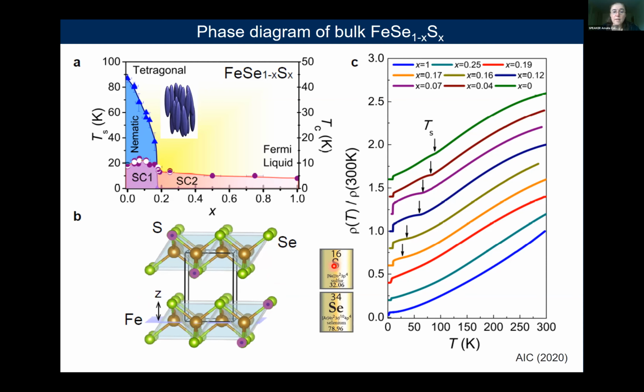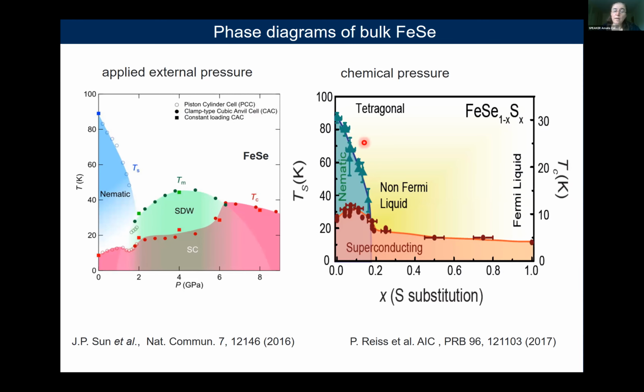So as sulfur is smaller than selenium, we also refer to this way of substitution, which is isoelectronic, that means we do not dope with electrons or holes. We refer to this way of doping as chemical pressure substitution. So this phase diagram is quite unique, as I said, because it does not contain any magnetic phase. We have the nematic phase suppressed with sulfur substitution to about 17%. There is a tiny dome of superconductivity inside, but there is no enhancement at the nematic endpoint here, and then there's a slow decay of the superconductivity, which survives all the way to the end compound.